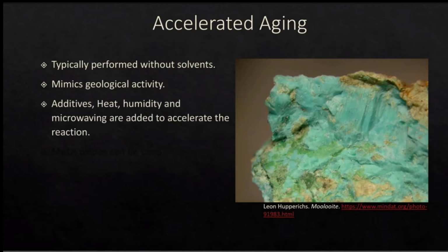In nature, we have a lot of time. Nature has a lot of time to make these reactions happen, though, and we don't have that time in the lab. And so what we do is we add additives, heat, humidity, and microwaving in order to accelerate the aging process. But once you've mixed the ingredients together, then there's nothing else to be done. You don't constantly disturb the sample as you do in a mechanochemical synthesis. You just leave it on the counter and basically let it react.